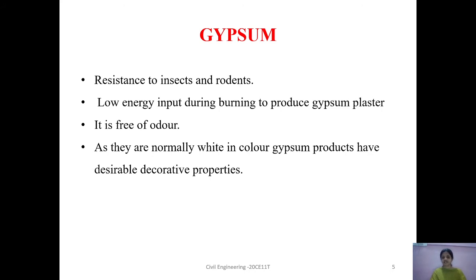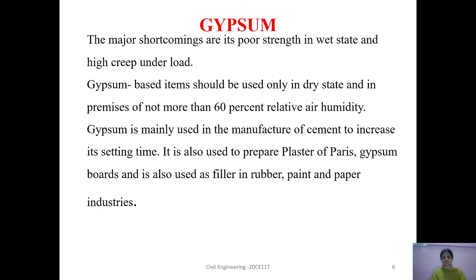As gypsum is normally white in color, gypsum products of any desirable decorative property can be produced. The major shortcoming of gypsum is its poor strength in wet state and high creep under load. Therefore, gypsum-based items should be used only in dry state and in premises where the relative air humidity is not more than 60%.